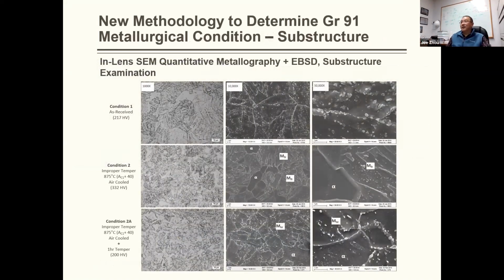The last case I will share, and later I'm going to talk more about this area, is a new methodology to determine the Grade 91 metallurgical condition, mainly on the substructure. 91 uses a tempered martensite microstructure. Optically, you cannot see much of the substructure details. Traditionally, people do the study using TEM. A TEM sample is so small you can only view about a 0.2 millimeter zone on a 3 millimeter diameter sample. To study a general condition, especially when the material is highly nonuniform, you have to run through 20, 30 samples to really pin down the case.